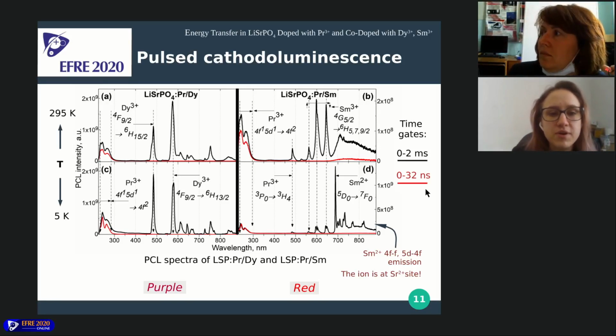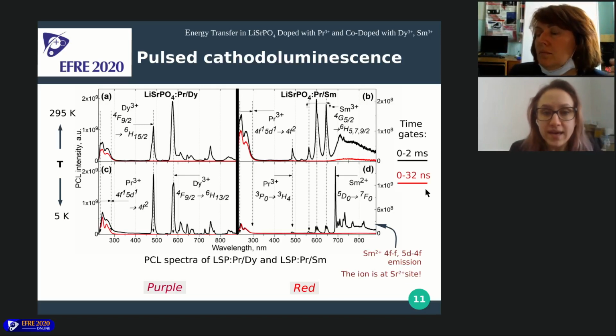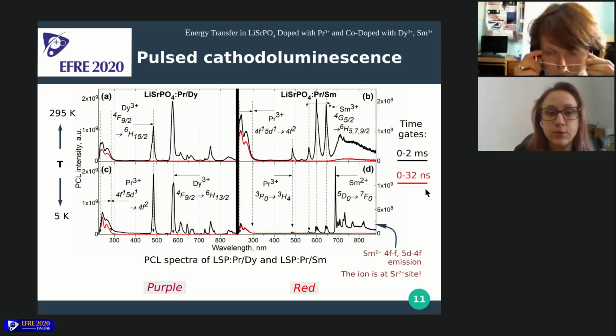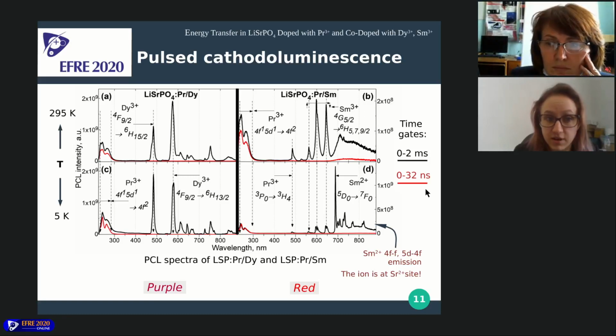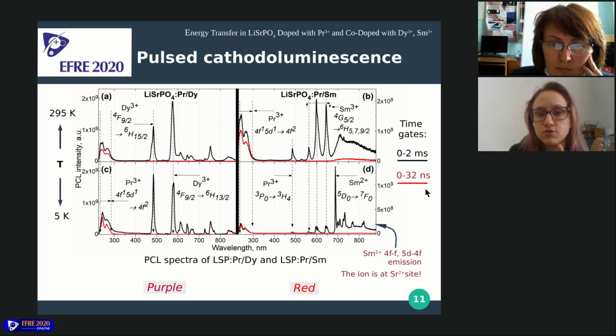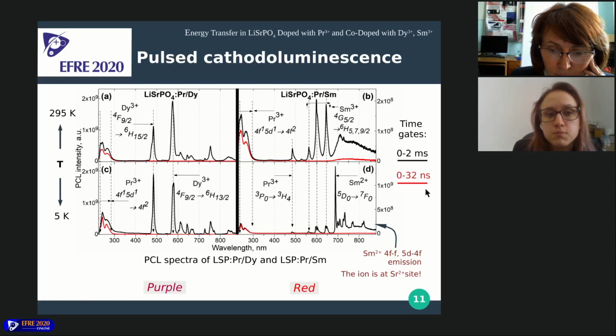Speaking about cathodoluminescence, we had to use different time gates because praseodymium 3+ is known for its fast interconfigurational transitions. And in order to distinguish this fast emission, we have to use a very short time gate, which is from 0 to 32 nanoseconds. Okay, but we are more interested in slow emission in visible range.